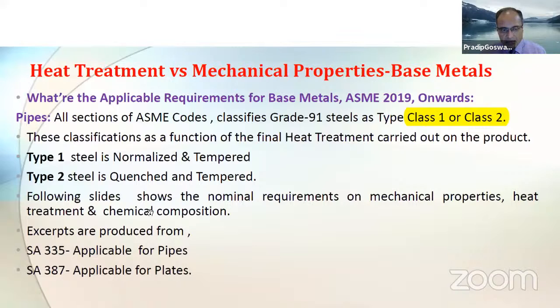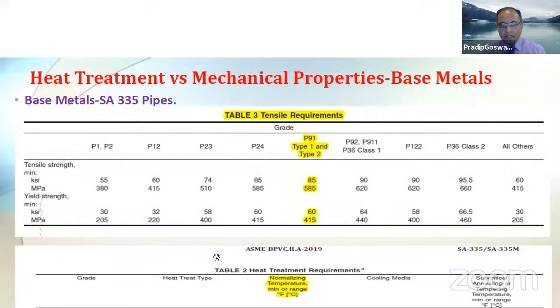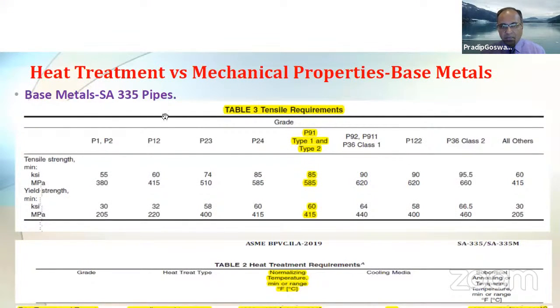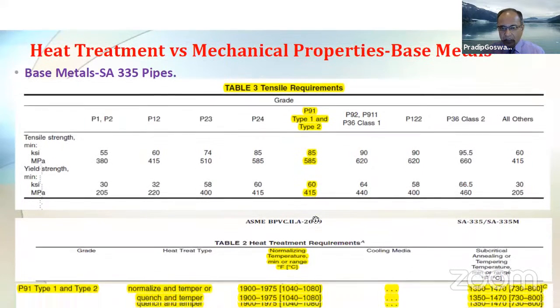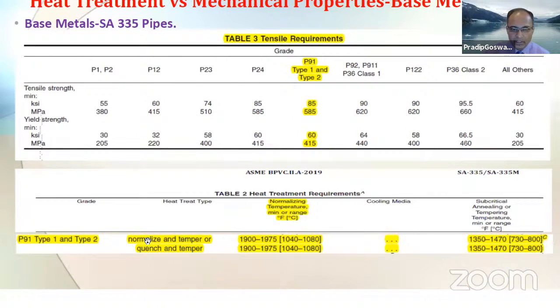Now, in the next few slides, I've tried to extract the salient mechanical properties, heat treatment, and chemical composition for the pipes as well as for the plates. For the pipes, the referred specification is SA335, and for the plates, it is SA387. When you see the SA335 pipes, these tables are extracted from ASME Section II Part A. Under P91, there are type 1 and type 2 alloys, and the nominal mechanical strengths are as highlighted. And there is a catch here, the heat treatment condition.